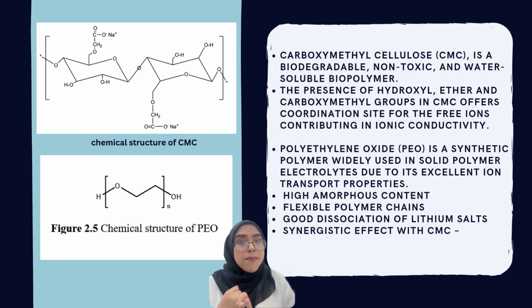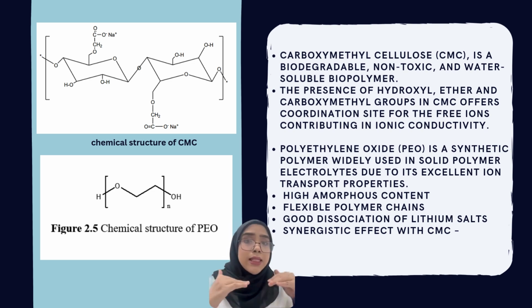I am using carboxymethyl cellulose, which is CMC, and polyethylene oxide (PEO) as a polymer host. Why am I using CMC? Because it is a biodegradable, non-toxic, and water-soluble biopolymer, and the presence of hydroxyl, ether, and carboxyl groups in the CMC offers coordination sites for free ions, contributing to the ionic conductivity. And I am using PEO because it is a synthetic polymer which is widely used in solid polymer electrolytes due